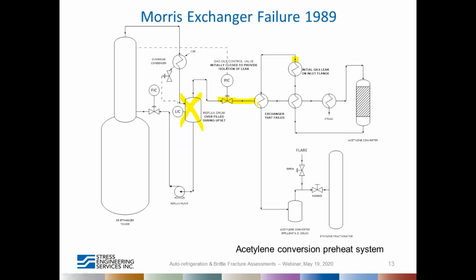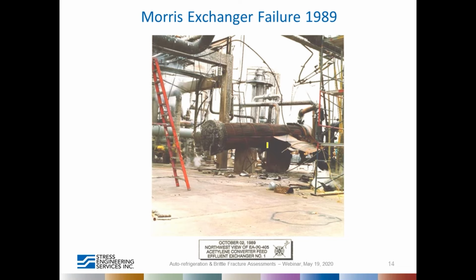And while they were working to resolve the issue, this particular valve was leaking, and ethylene, at a very low temperature, was making this particular heat exchanger cold. So when the plant started back up, the pressure increased, and the low temperature of the material induced brittleness, and the high pressure resulted in this explosive failure. So this was the remains of that particular heat exchanger.